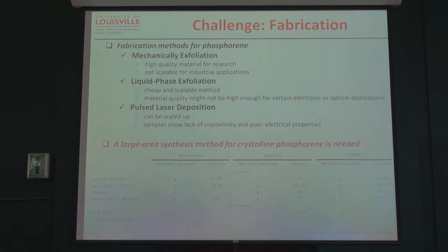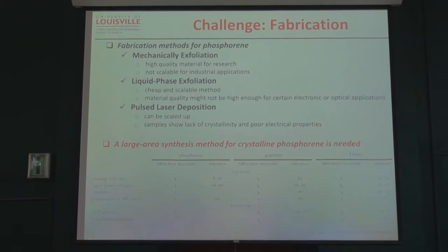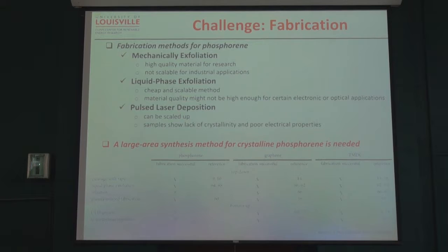Let me ask about the third type. Pulse laser deposition? Yeah. So that's usually a UHV system, high vacuum system. You just focus a high power pulse laser beam, then it just deposits onto the substrate. That way also you can control the number of layers, but they are not very highly crystalline. You have crystallinity, but not so good. But good for some lab scale studies.